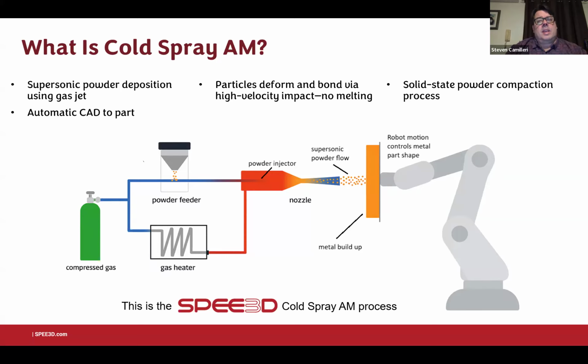And indeed, we also get this additional cold work and dynamic recrystallization, for those that believe in that, which gives us beneficial material properties as well, which you don't get at all in PM. It's very unusual to get any kind of dynamic behaviors in your compact in PM. So if you think about cold spray as a particle by particle pressing process, then indeed what we're doing is a standard PM route for making a material. We press and sinter. So it's an unusual lens to look through when thinking about additive manufacturing, but we're finding more and more it's a benefit to think about it that way.